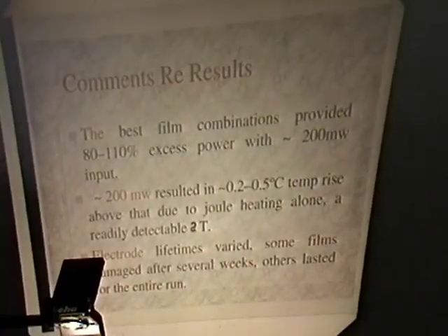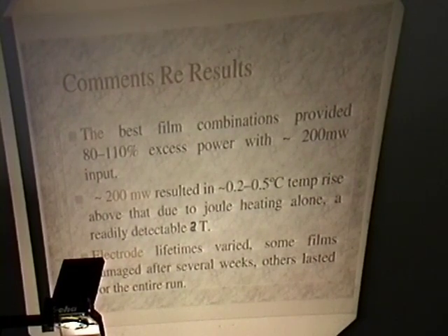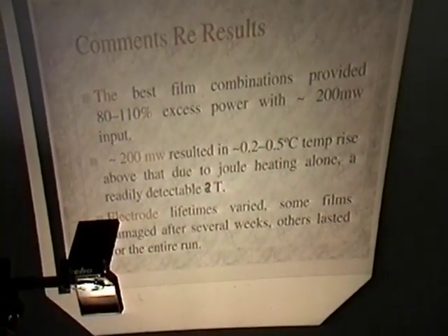So the conclusion of that was that with this very simple type of experiment, we're talking about an electrode yay big. The best film combinations produce something like 80 to 110% excess power with 200 milliwatts in. The temperature rises are small in this type of calorimeter. It's something like 0.2 to 0.5 of a degree, but that's quite detectable with the sensitivity we have. The problem that still remains, which we haven't completely cured from ICCF-8, is that these films do not always stay on the substrate, and we've been working on ways to overcome that difficulty.